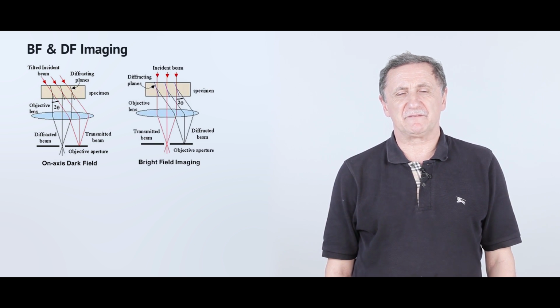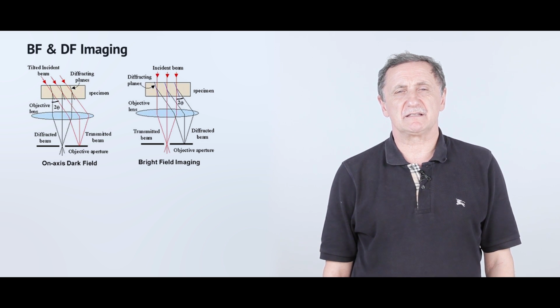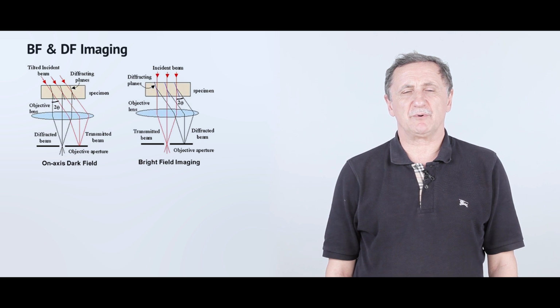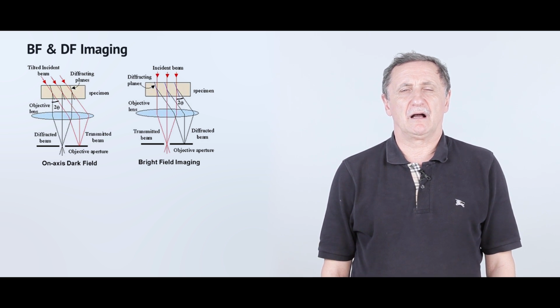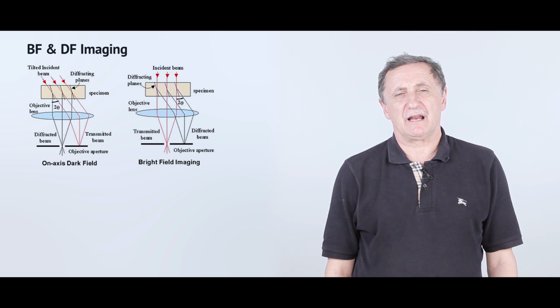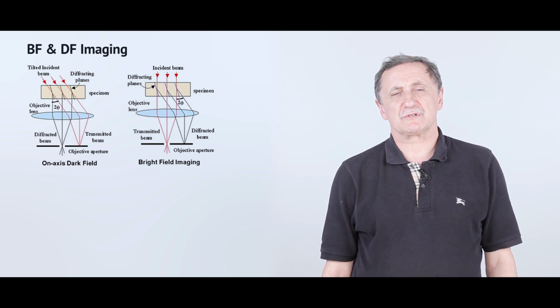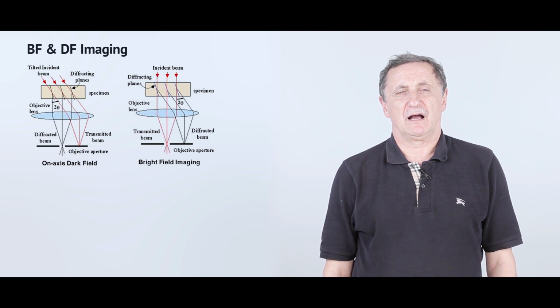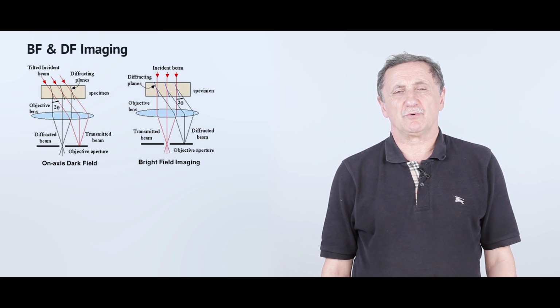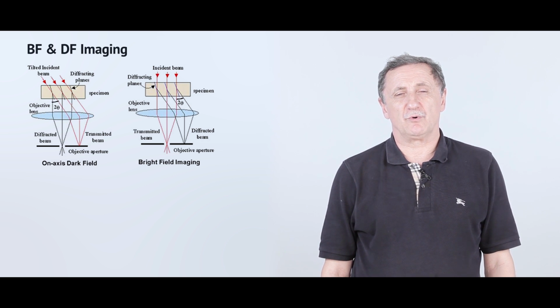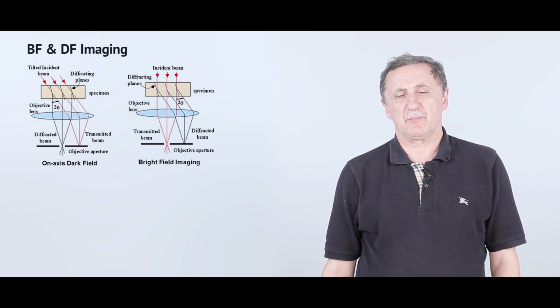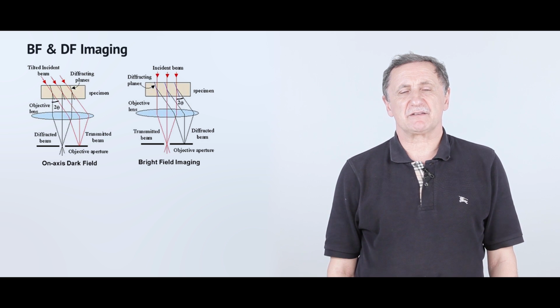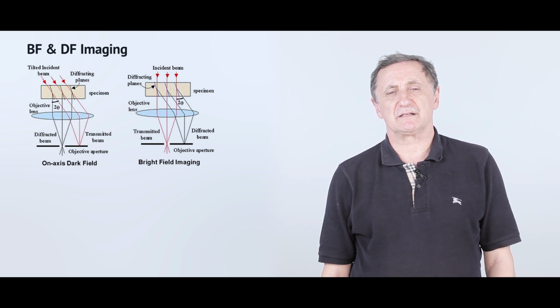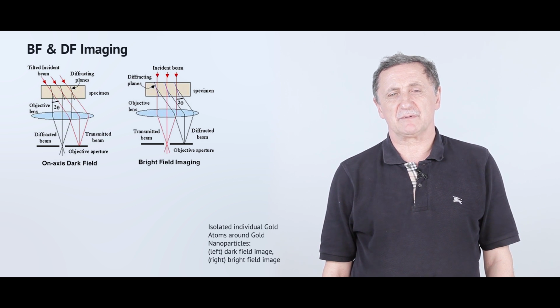Now let's start with the bright field image. In this case, we have the incident beam passing through our sample, and we are monitoring only the transmitted beam electrons which pass through with almost no change of their initial direction of propagation. You can imagine that through gold, because it has a much higher density than carbon, far fewer electrons will pass through as compared to the carbon substrate. Because of that, on the image, the gold particle looks darker than the carbon substrate.